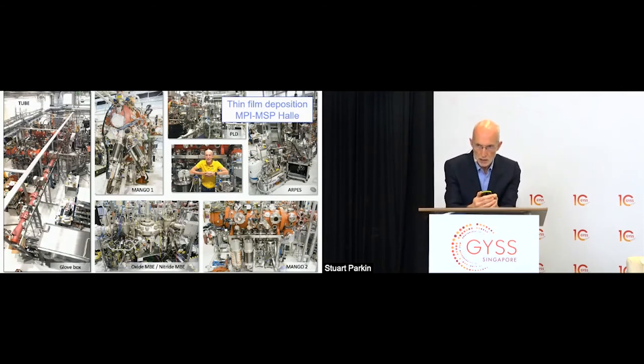And again, there's no time to discuss this, but we have, for example, molecular beam epitaxy systems for depositing oxides and nitrides. We have a glove box for exfoliating 2D materials. And we have our own system, I call it Mango, which has up to 44 sputtering sources, magnetron and ion beam sources. And all these systems are designed so that the source materials can be rapidly changed while the rest of the system continues to operate. So this is a very exciting development that we've developed over the last few years to enable us to accelerate our discovery of interesting atomically engineered materials, both for spintronics and for superconducting applications and for other applications and science.